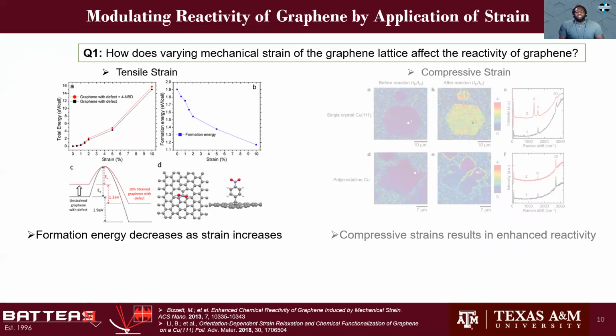And so literature shows a relationship between strain and formation energy. In this first work referenced here, tensile strain was applied to a substrate with graphene mechanically exfoliated to the surface. And it's been demonstrated that with an increase in strain, a decrease in formation energy was observed. This decrease in formation energy means that less energy is needed to initiate this reaction. Also, it should be noted that in this experiment, wrinkles were also present during the tensile strain experiment due to slippage between graphene and the substrate, since tensile strain was actually applied to the substrate and not directly to graphene.